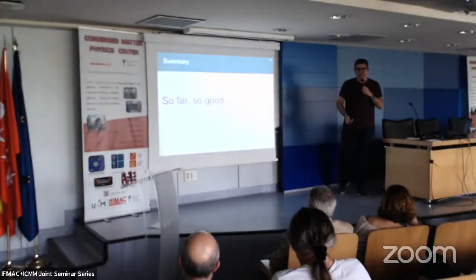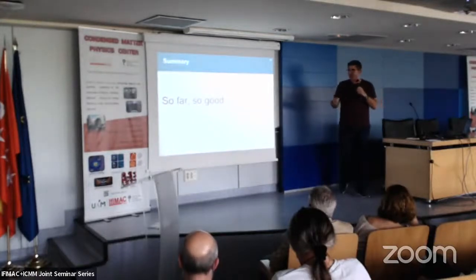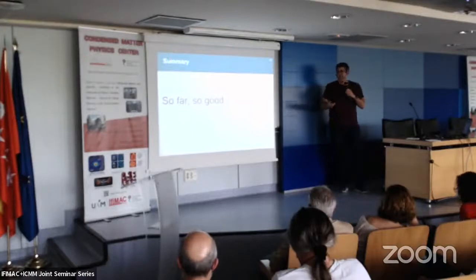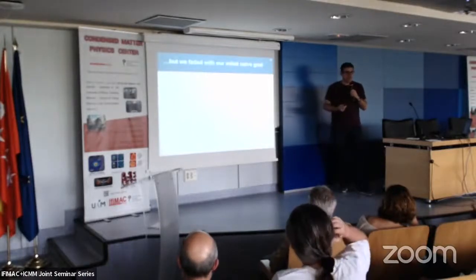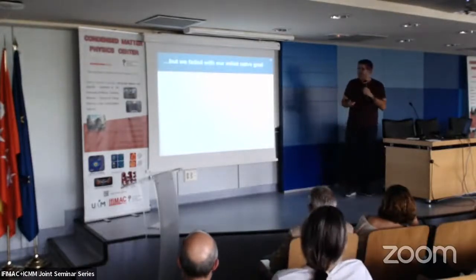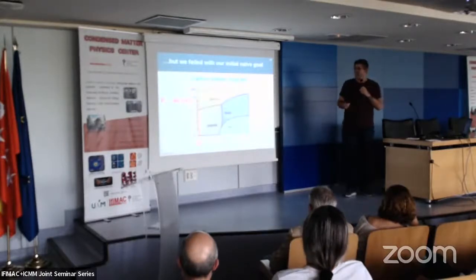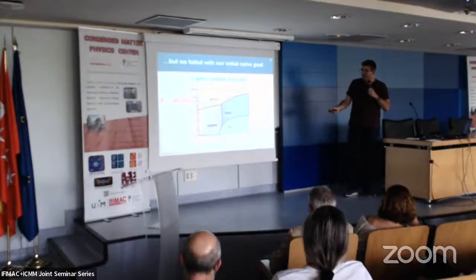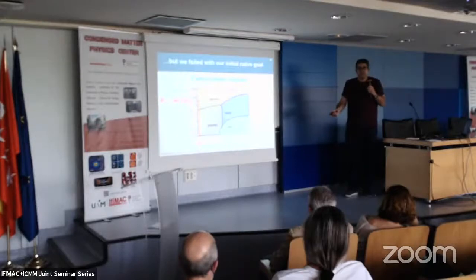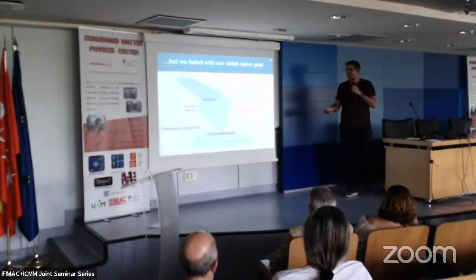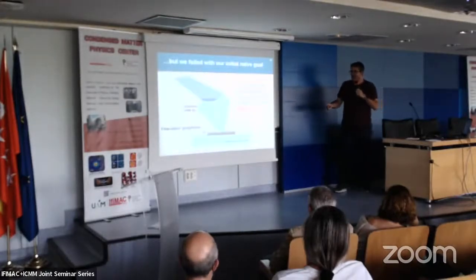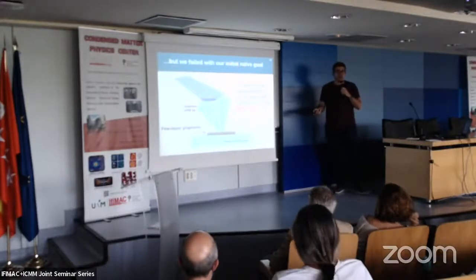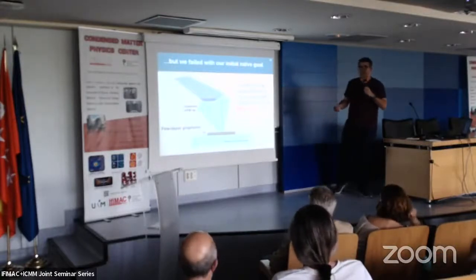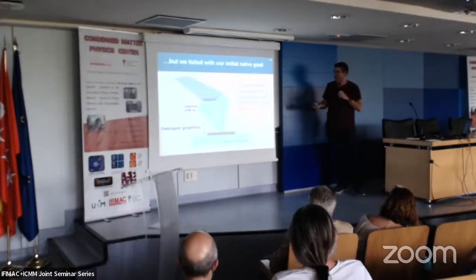But as Christina mentioned at the beginning, not everything is success. The main objective of our initial goal has failed. When all this started, because we saw the carbon phase diagram, we thought, okay, at room temperature, if I go up to 40 gigapascals, I will turn graphite into diamond. Let's do that, because we can put pure layer graphene on a diamond substrate, get our diamond tip, push beyond these 40 gigapascals, and turn pure layer graphene into diamond. Okay, we will get rich very easily.